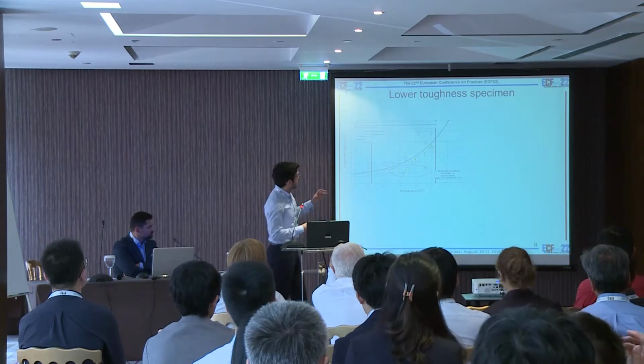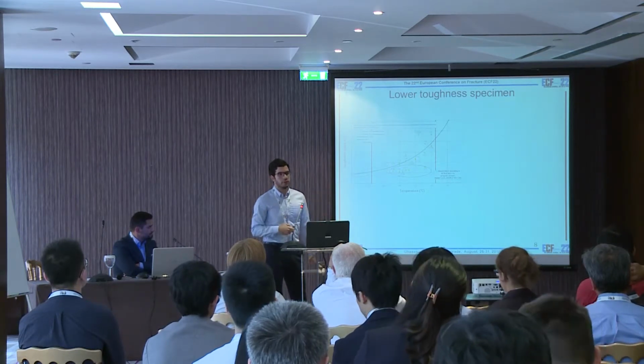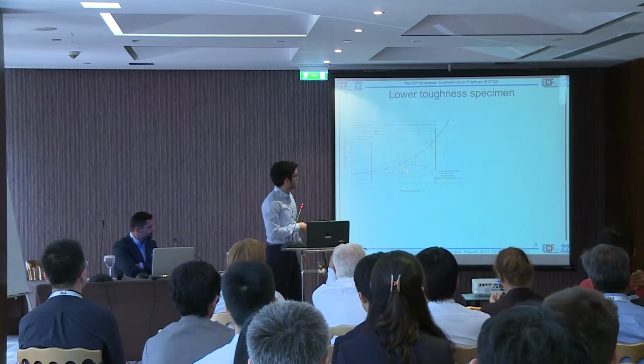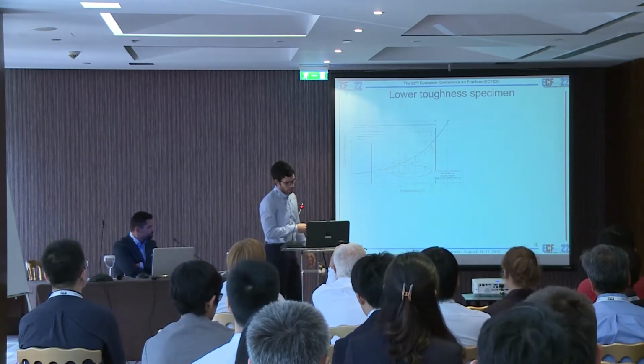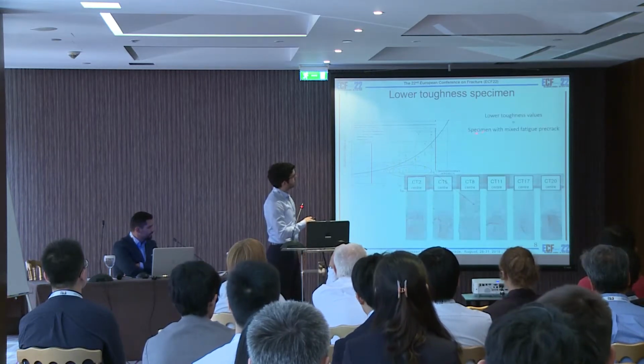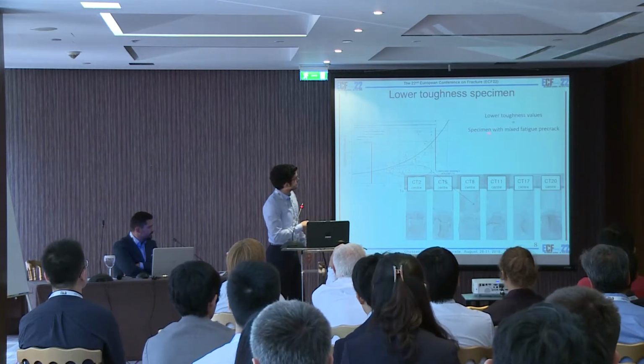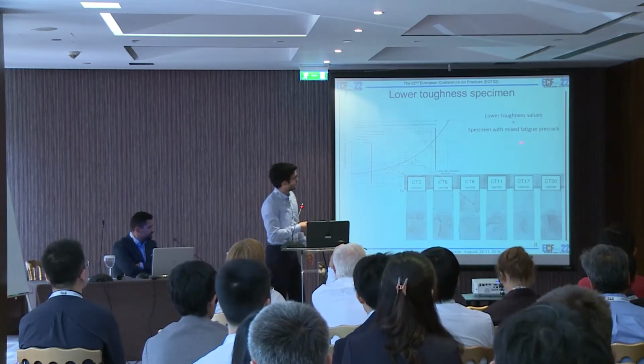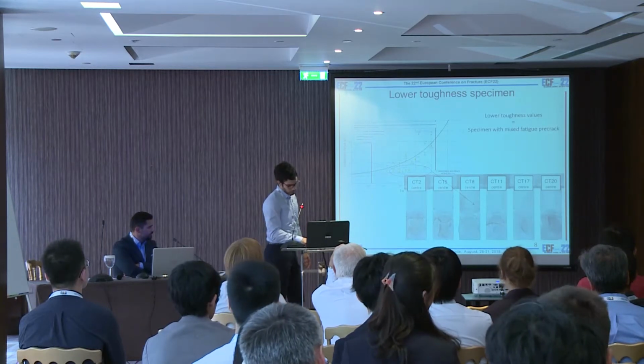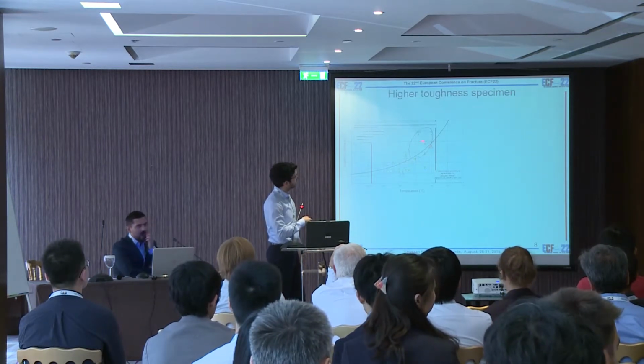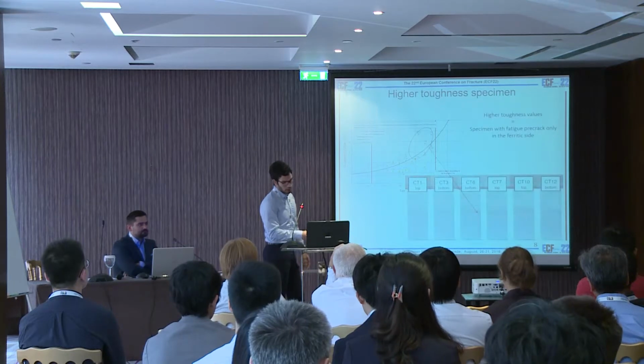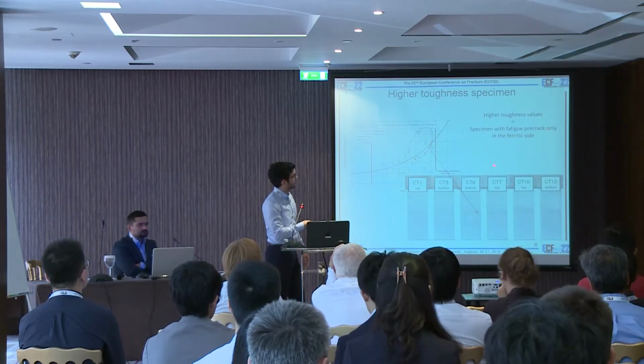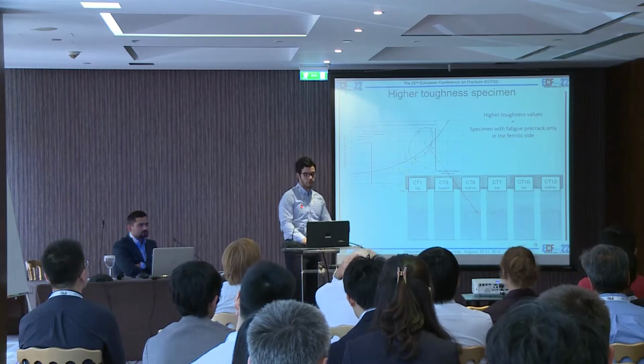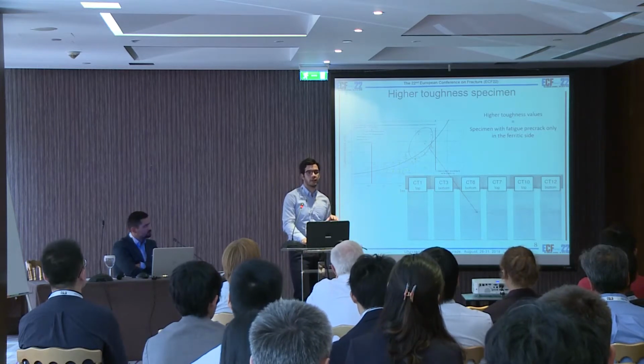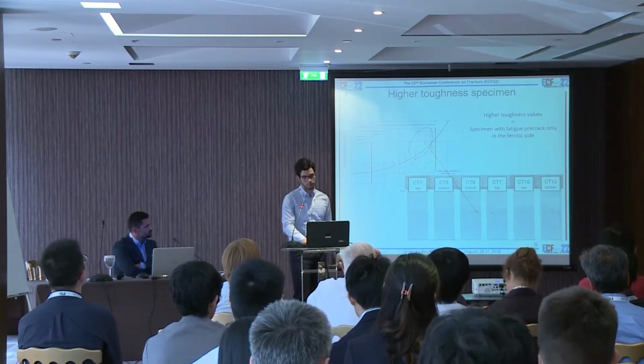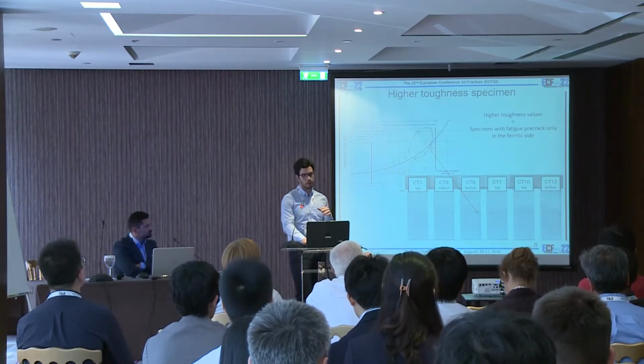So, when we try to link the composition of the fatigue pre-crack to the toughness values, we notice that the lower toughness values are always for specimens with mixed fatigue pre-crack, as we can see here. And on the other hand, the higher toughness values are for specimens with fatigue pre-crack only in the ferritic side. So we can conclude that the presence of austenite in the fatigue pre-crack plays a major role in toughness lowering.